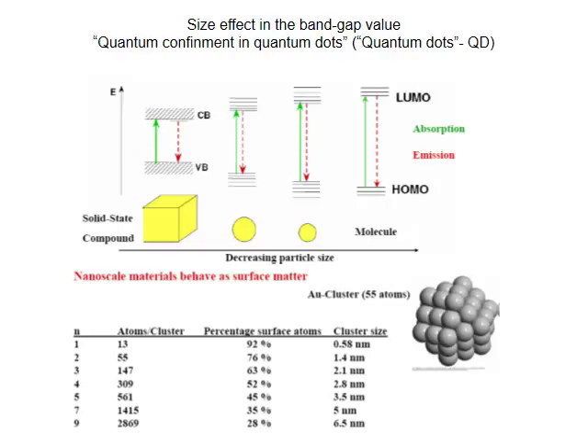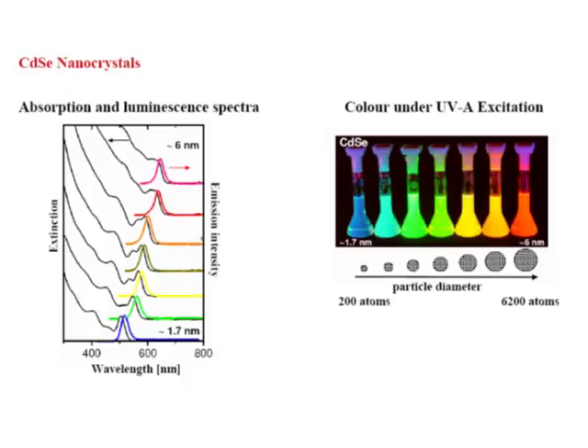Concerning materials, the interesting point here is that the quantum dots behave as surface matter, since most of the atoms are at the surface. This table gives you an idea of that feature. A 2.1 nanometer crystal of gold atoms will display 63% of the atoms at the surface. This nanometric size will lead to novel chemical and optical properties that are, in fact, at the heart of what we call today nanotechnology. These are some absorption and emission spectra of CdSe nanocrystals, cadmium selenide. The quantum size effect leads to shifts in the spectra as a function of the crystal size.